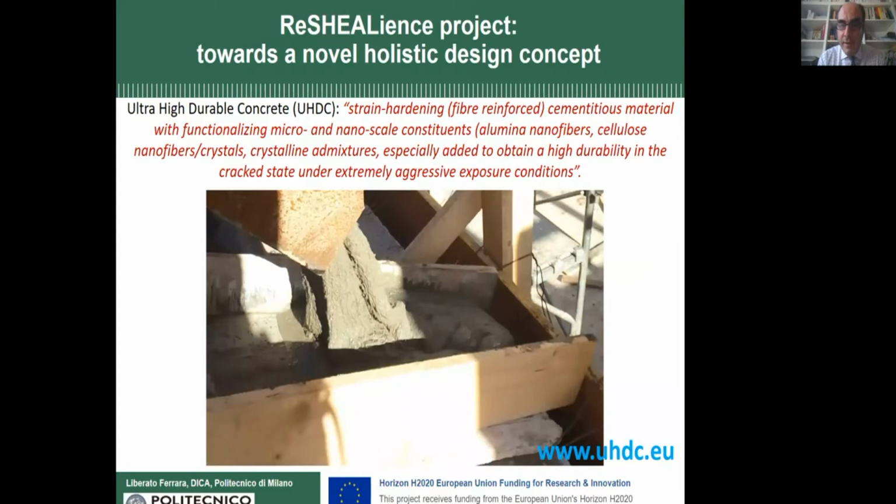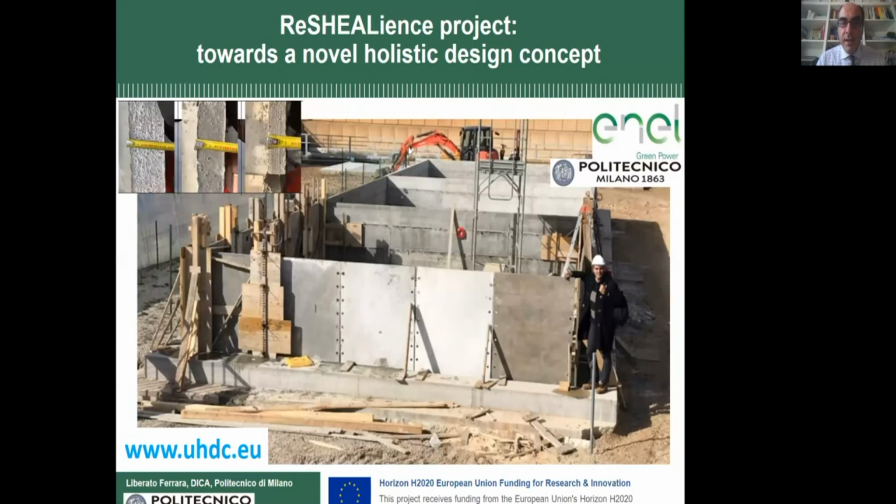If you start from the far side, you have the regular reinforced concrete, the continuous wall UHDC concrete, and the precast. And you can see in the inset on the top left the reduction of thickness from 10 centimeters to 6 centimeters down to 3 centimeters. These precast square slabs are 3 centimeters thick.